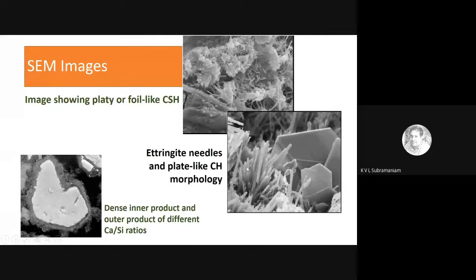And basically, if you look at a cement grain, you see these reaction products that have formed around it. The bright whitish thing is the cement grain. You see the reaction product that has formed around it. The black in this SEM image is water. And basically what has happened is that the reaction product forms around the cement grain, and this reaction product is primarily calcium silicate hydrate.